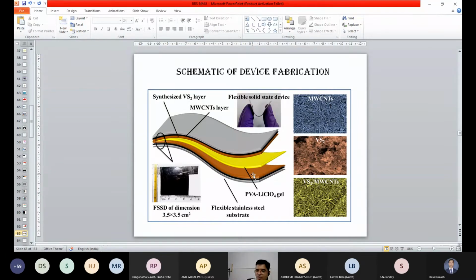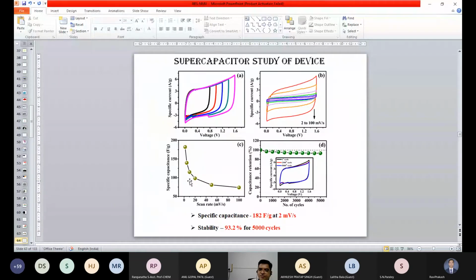Then we have pressed that overnight using certain pressure, so that the gel can penetrate inside the high surface area of the carbon nanotube, which is coated with the vanadium sulfide. Then these two electrodes, we have used Scotch tape, right? There is no proper sealing, we have just used tape, and this is one electrode and this is another electrode. So the dimensions are about 3 by 5 centimeters square. And this device we have tested, this is a large area, right?